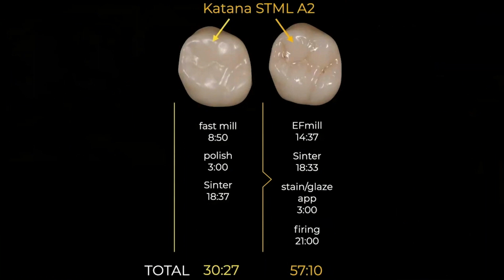And then I said, well, let's see what if I wanted to go all out and use the best milling and stain and glaze application. Let's see how much time that would take. And I got to a little over 14 minutes for the extra fine mill. The sintering was about 18 minutes. And then the time it takes to apply the stain and glaze. And then in this case, I fired it in my speed fire. So when you're firing the stain and glaze in the speed fire, it is going to take quite a bit of extra time if you're trying to do it immediately after you've sintered it, because the oven has to cool down from the sintering temperature and then do the glazing.